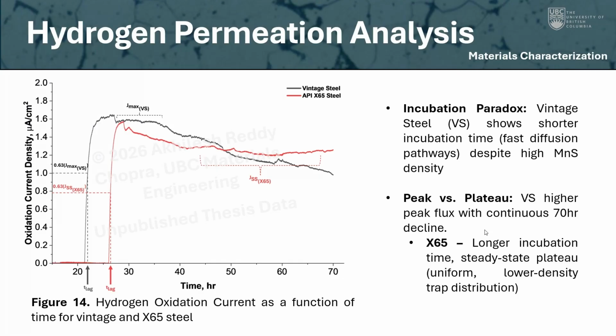But then, as we see over time, over the next 70 hours for vintage steel, we see a continuous decay instead of a steady state plateau, which is observed in X65. And this essentially tells us that these inclusions are, over time, continuously trapping hydrogen. And so it's slowing down the mobility of hydrogen through that steel, and we're not seeing an equilibrium develop over